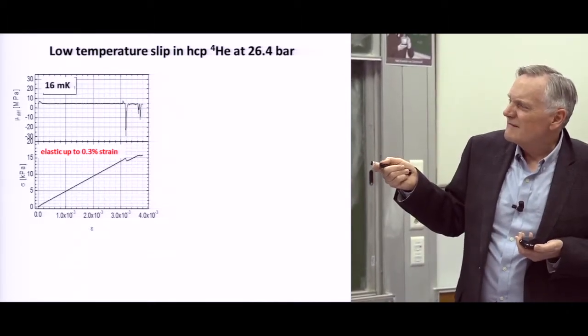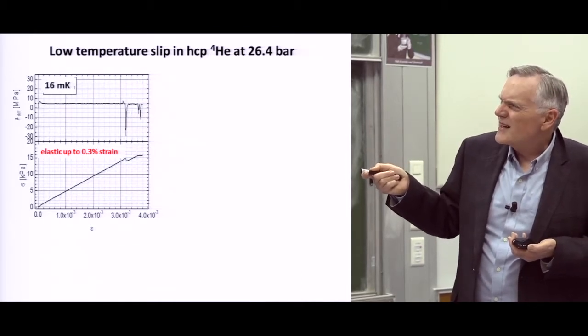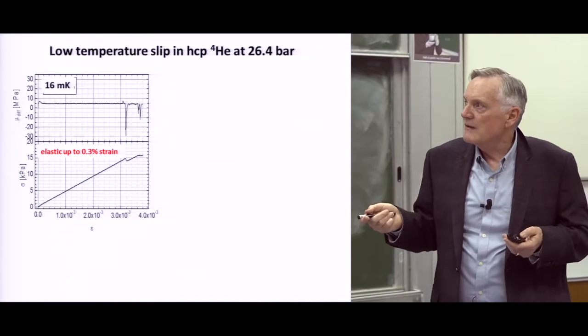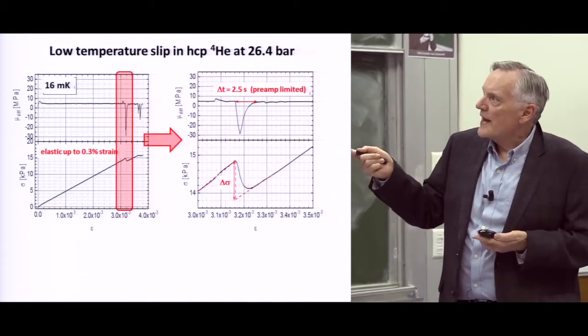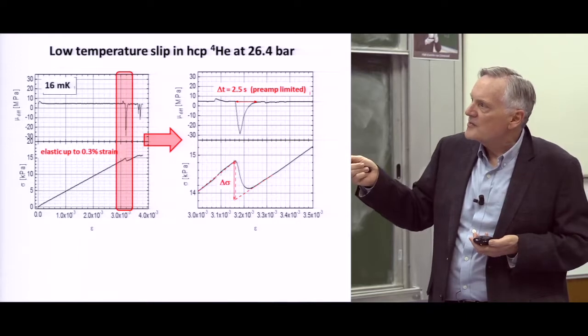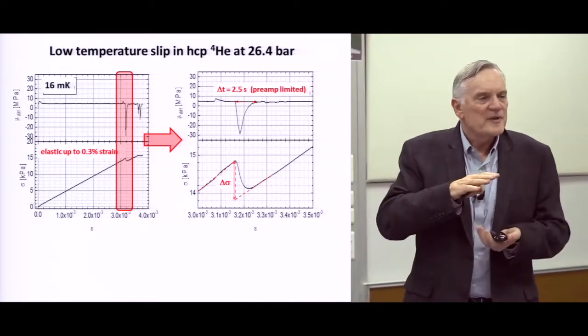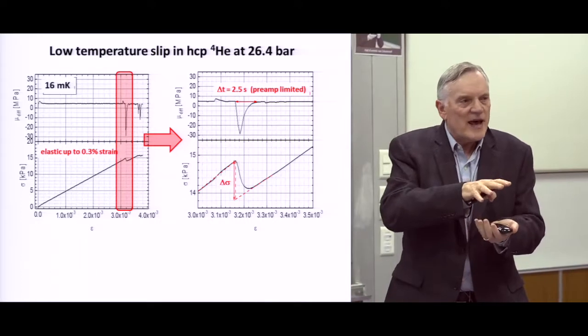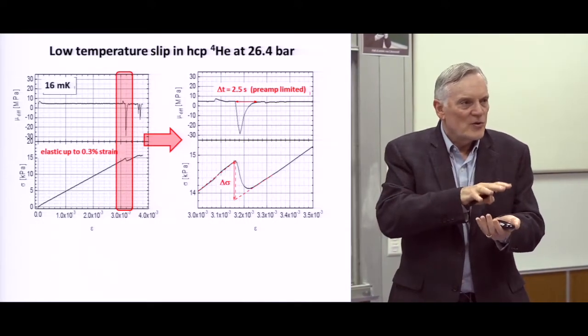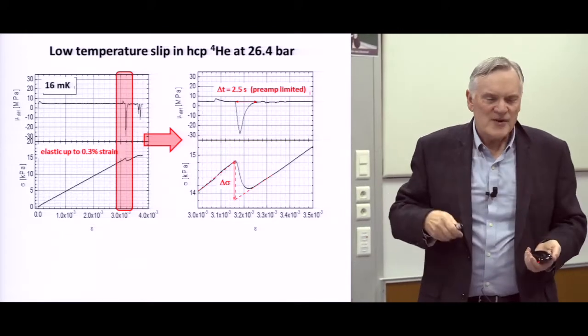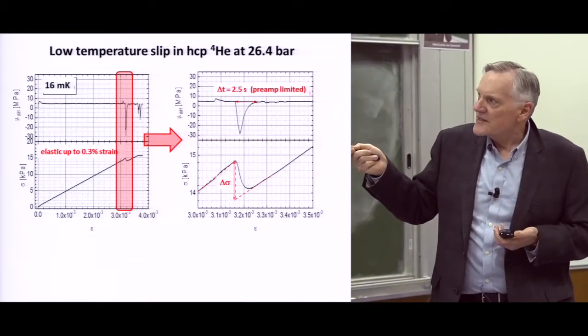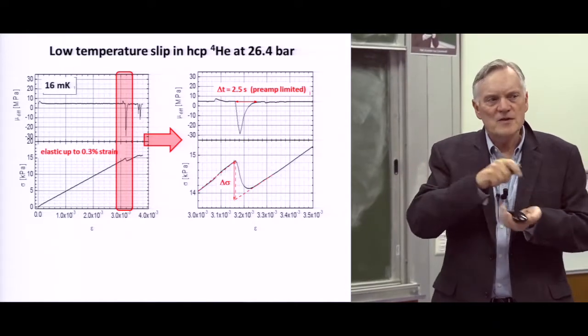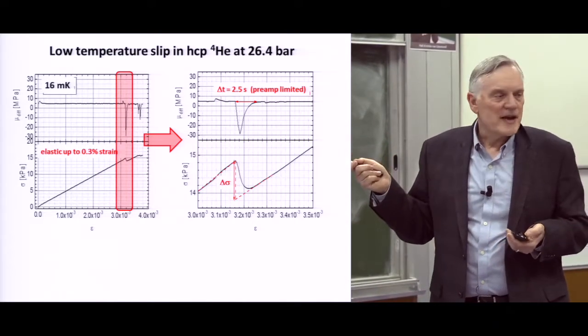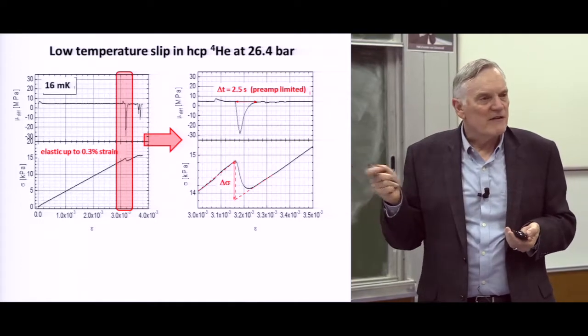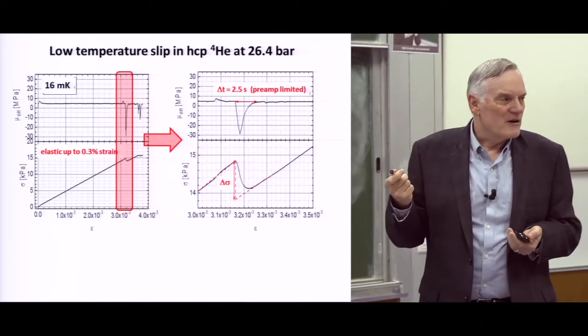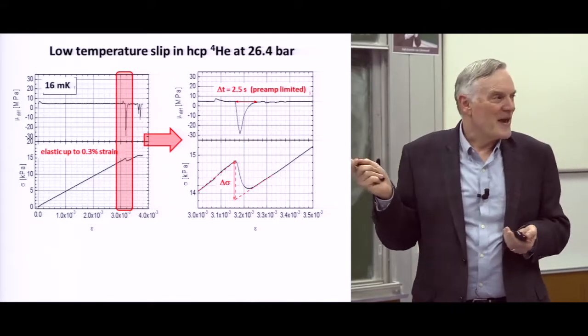And this is the current we measure, and this is the integrated signal. You'll see a little glitch there, where something happened at about 0.3%. If you blow that up, you see there's a dip in the signal. That corresponds to a fairly sudden drop in the stress. So you strain and strain and strain it, and then suddenly something jumps, it slips, and you relax some of the stress that you built up. This one corresponds to relaxing about 5% of the total stress, and it seems like it happens over about 2 seconds. But it's actually faster than that, because we have a preamp with a bandwidth of 0.3 hertz. So this is totally due to the bandwidth of the preamp.